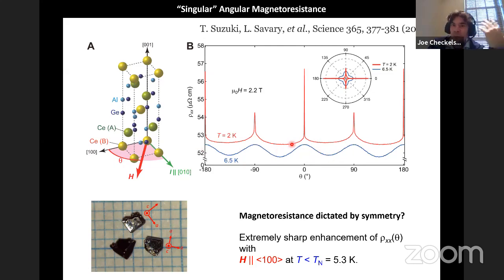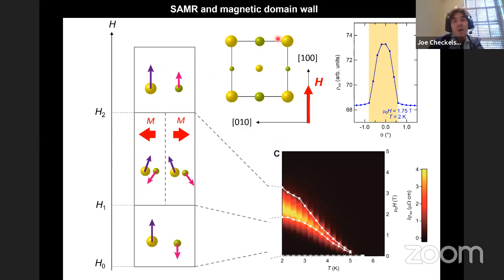But for whatever reason, when we went below the magnetic ordering temperature down to 2 Kelvin, superimposed on top of this, we saw this huge and very sharp response, which was really at the time unlike anything I had ever observed previously. The solution to where this came from was a lot of conversations between Lucille Savary, who was an MIT postdoc at the time and is now a faculty member in France, and Leon, who is, again, speaking next, through understanding how, in a different way, topology and magnetism could give rise to a new kind of magnetotransport effect. So let me walk you through the picture we have of how this works.